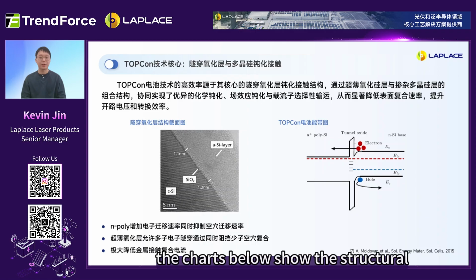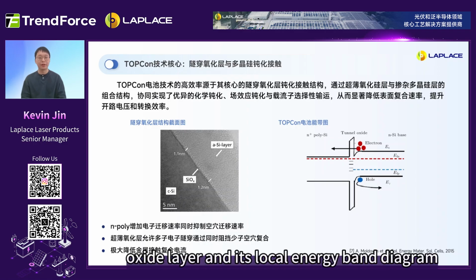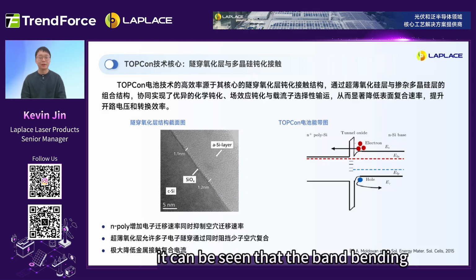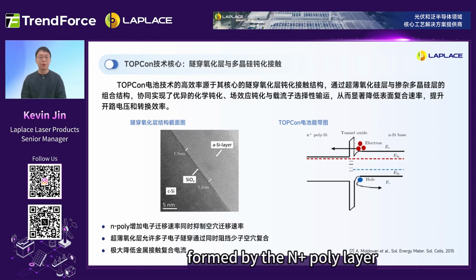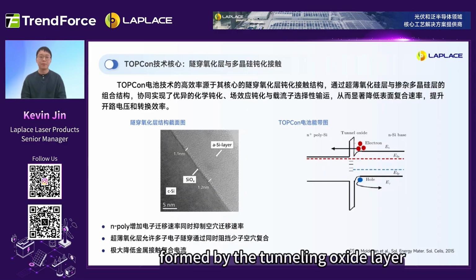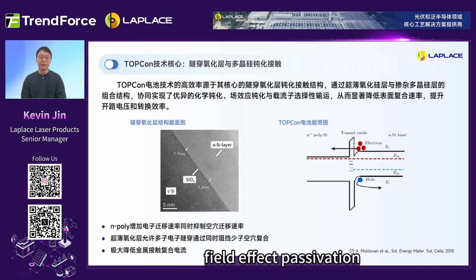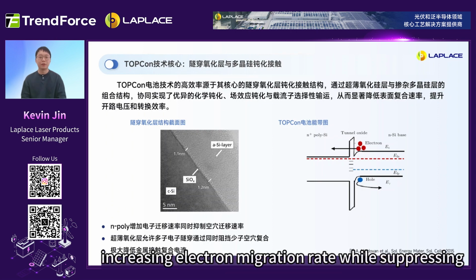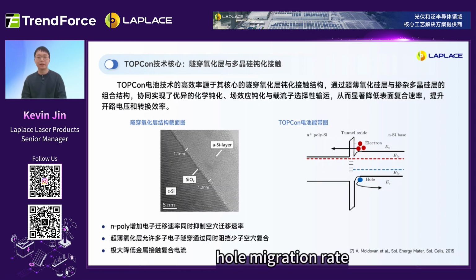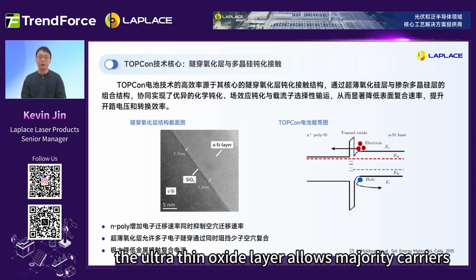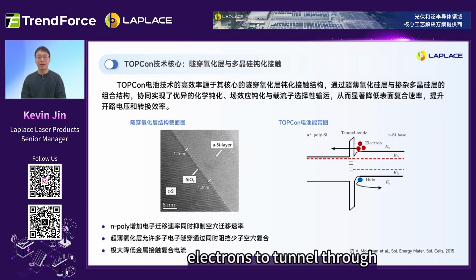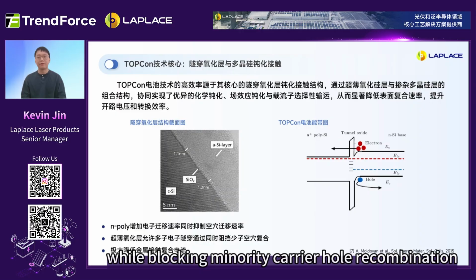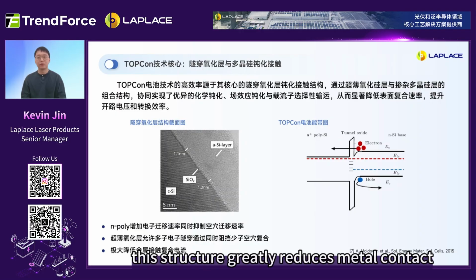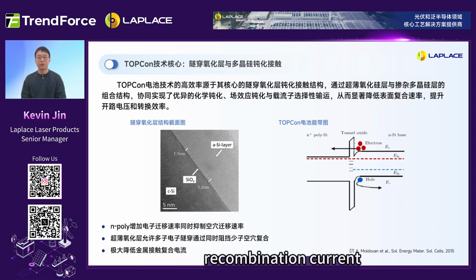The charts below show the structural cross-section of the tunneling oxide layer and its local energy band diagram. It can be seen that the band bending formed by the N+ poly layer and the potential barrier formed by the tunneling oxide layer can effectively create carrier selectivity and field effect passivation, increasing electron migration rate while suppressing hole migration rate. The ultra-thin oxide layer allows majority carriers, electrons, to tunnel through while blocking minority carrier hole recombination. This structure greatly reduces metal contact recombination current.